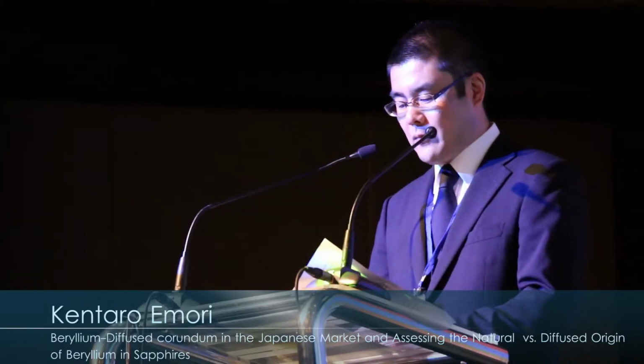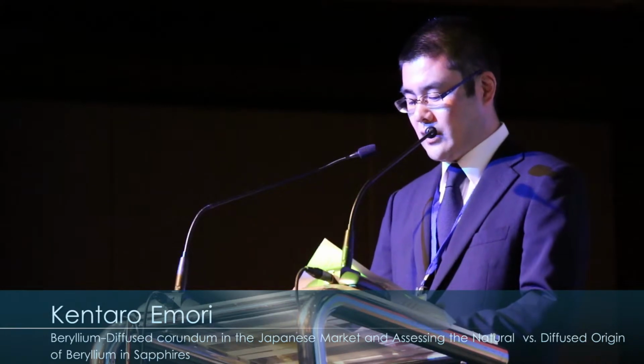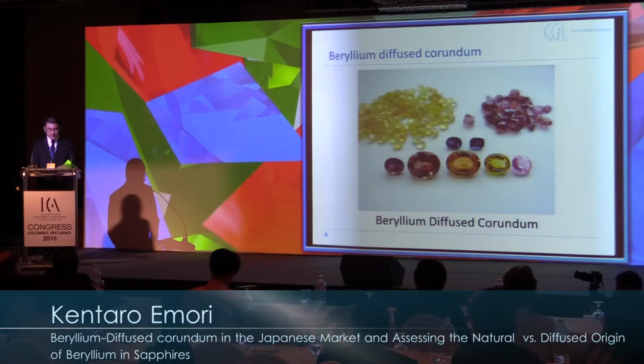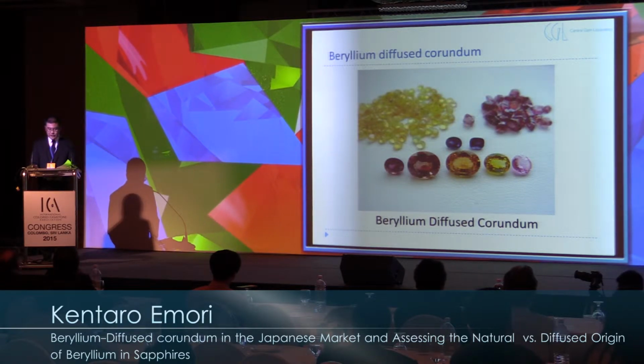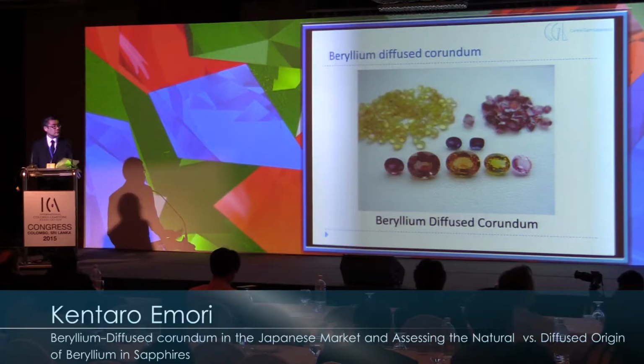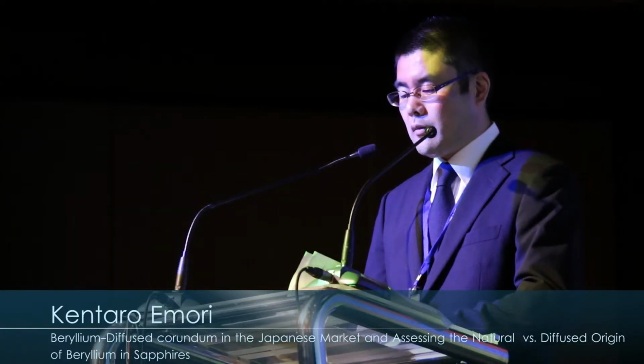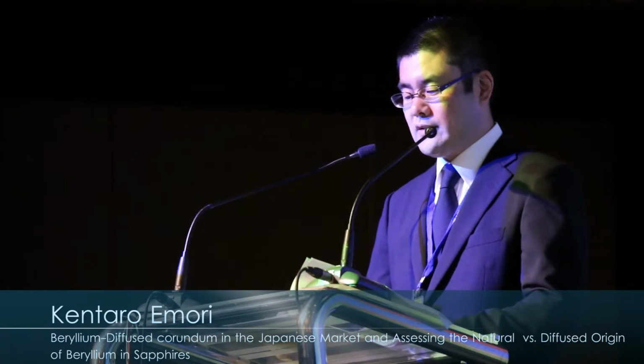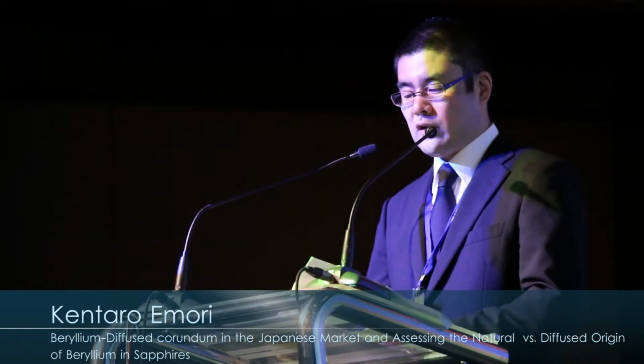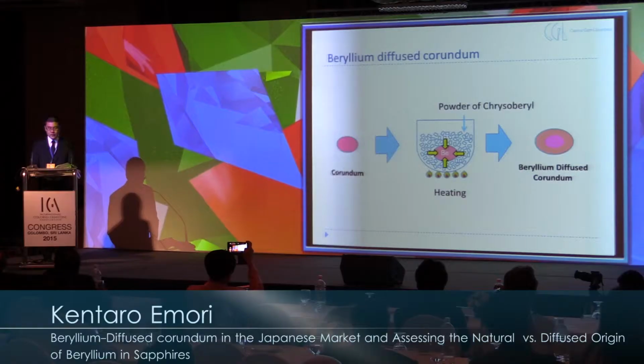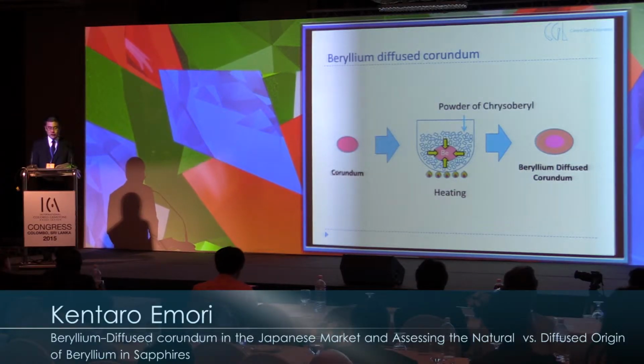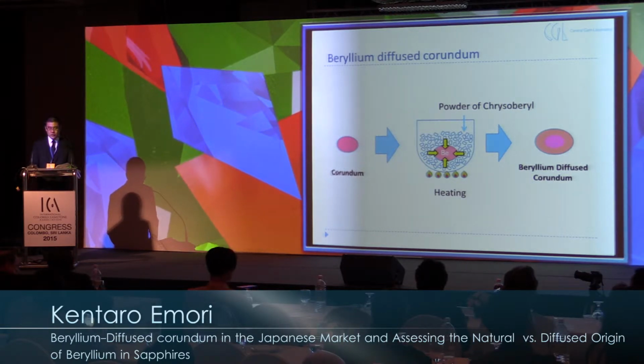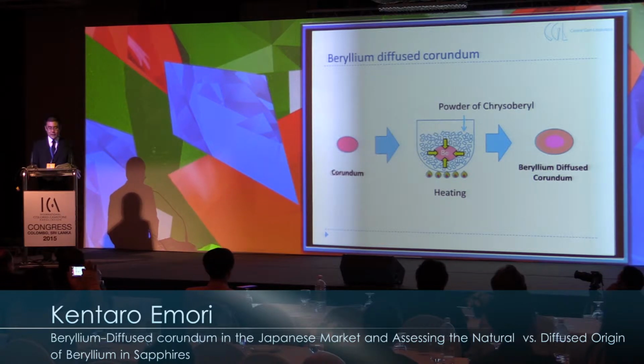Sapphires in this photograph are beryllium-diffused sapphires. Beryllium-diffused corundum has been seen from 2001, but we can still see it over the decade. Beryllium-diffused treatment means the technique in which beryllium is diffused into the corundum from the surface directly. When corundum is heated with powder of chrysoberyl, beryllium from chrysoberyl diffuses into corundum, and corundum changes its color. In pink sapphire, the beryllium-diffused layer becomes orange, and it can be seen as a padparadscha color.